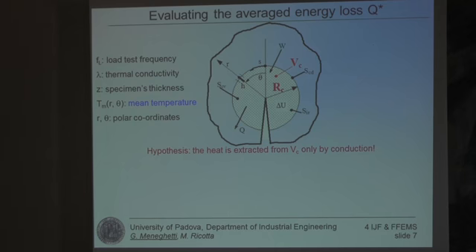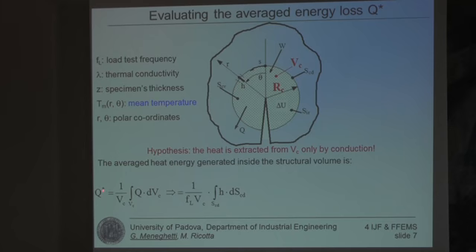We made some experiments in the laboratory. Of course, heat dissipation occurs by conduction, convection, and radiation, but we proved that heat conduction is by far the most active mechanism to extract the heat from the crack tip. So we suppose that heat conduction occurs through the boundary of the structural volume. All testing parameters are defined, and so we can evaluate the average heat loss by integrating the specific heat flux through the boundary of the structural volume.